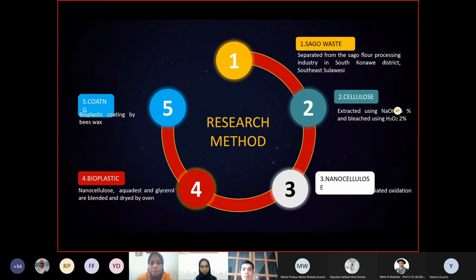TEMPO solution was freshly prepared by mixing 0.2 gram of sodium bromide and 0.04 gram of TEMPO in 100 ml distilled water. Bleached sago specimens were added to the solution under stirring. Then sodium hypochlorite in water was added to the mixture and allowed to react for 3 hours under stirring. At the end of 3 hours, 5 ml of ethanol was added to stop the reaction. The resulting sediment was then put into a dialysis membrane bag and soaked with distilled water for 1 day.